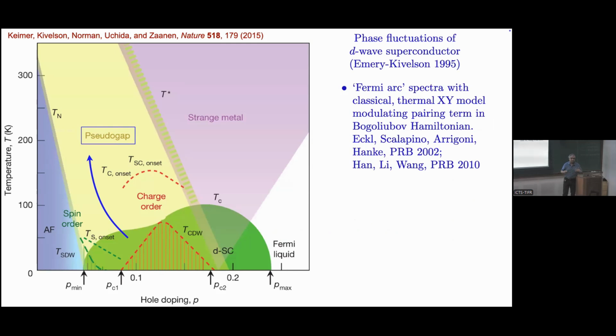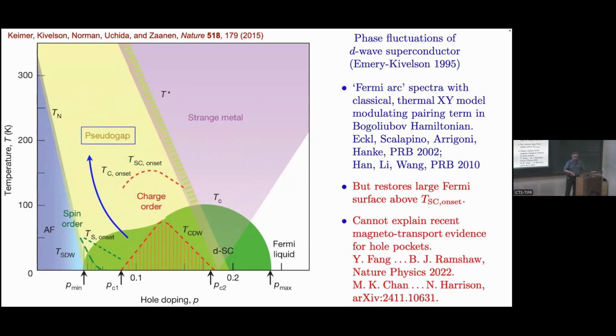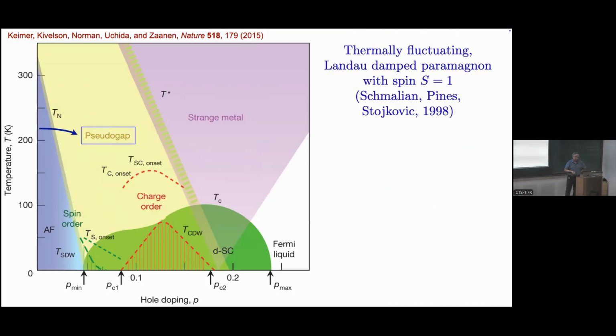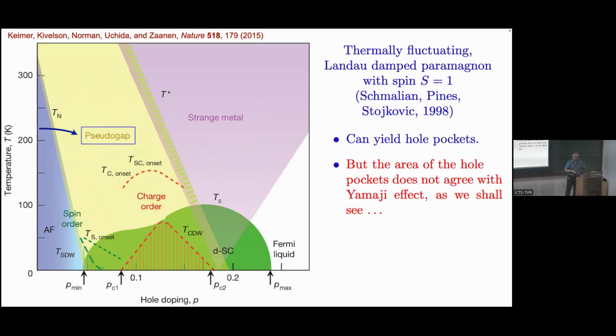Yeah, very quickly. There is, of course, no shortage of theories of the pseudogap over the years. The earliest was to think in terms of phase fluctuations of the d-wave superconductor. That can kind of explain the Fermi arcs, but it has problems. When you get well above here, you should just see the large Fermi surface, which you don't once you're above Tc onset. And there's no way to explain the magnetotransport. In this theory there are no pockets, only arcs, so it can't explain the magnetotransport. There are also theories based upon fluctuating antiferromagnetism. These have an easier time explaining magnetotransport. That's fine, but the area, which is now known quite precisely, doesn't work, as I'll show you.